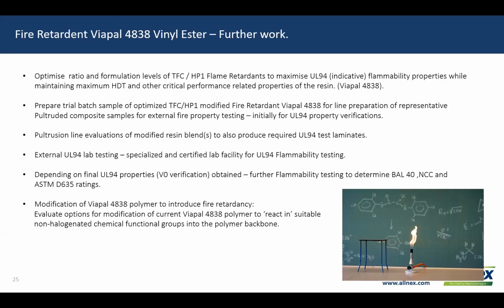But we also need to produce some test laminates and pultruded representative laminates for outside fire testing as well. There'll be external UL94 fire testing, and there are a few options here as well, of course, as USQ's rig, which we obviously initially want to do some internal testing on. Depending on those properties, and we can confirm a V0 verification is required, then we can look at further outside flammability testing for BAL 40, the NCC, and the ASTM D635 requirement. That's a fairly easy self-extinguished test to pass. So mainly the BAL 40 and the NCC will be interested to see how we go there once we've optimized the formulation.